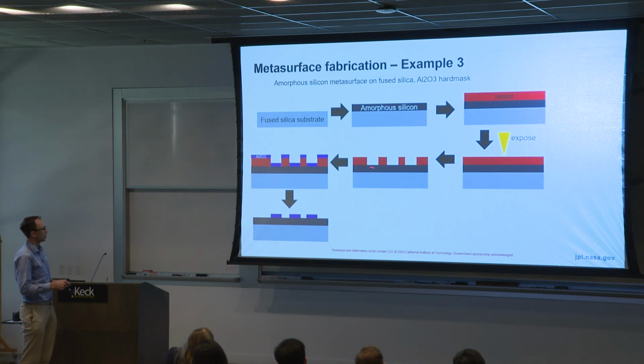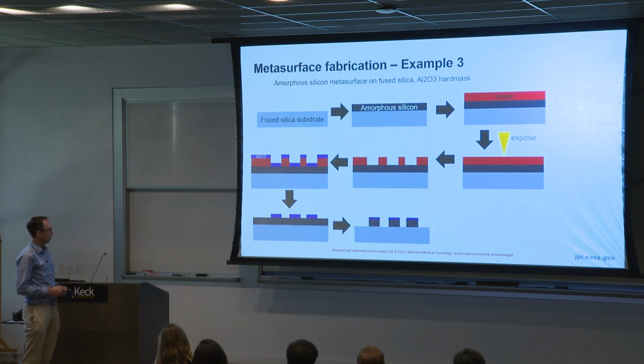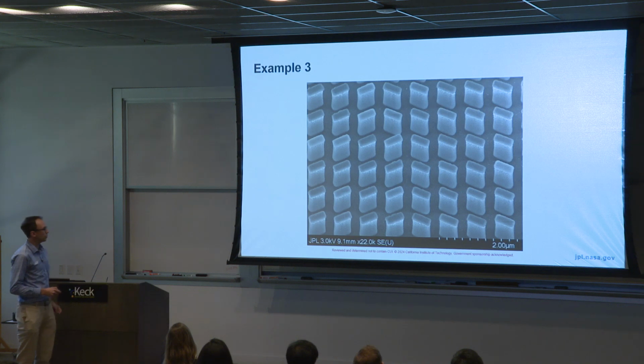So this is something kind of important to keep track of when you're designing these processes. And honestly, it's quite easy to make a mistake and end up with pillars where you thought you wouldn't have them. So then you use your favorite anisotropic etch and you define these pillars into the amorphous silicon. You would stop when you hit your glass substrate. And then if you desire, you remove the aluminum oxide. So the end result might look something like this, where you have these amorphous silicon pillars standing on fused silica.